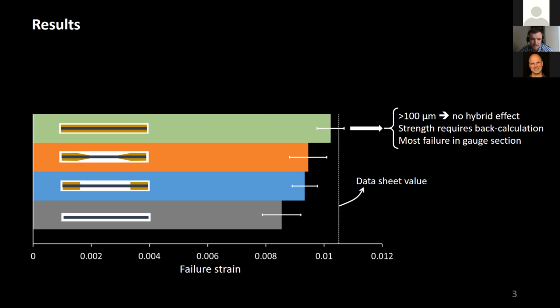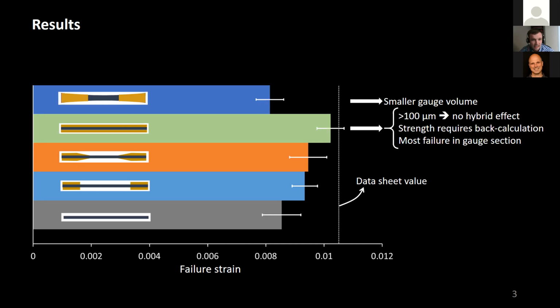The great thing about this test is that you know where the failure happened, and most of the time that actually happens away from the end tabs, nicely inside the gauge section. And that is a big problem with all the other specimen designs, for which if you don't know where it failed, you cannot know whether that particular test was a reliable test, because you don't know whether it failed under uniform stress conditions. So then we had big hopes for the butterfly design, but unfortunately this was in some regards